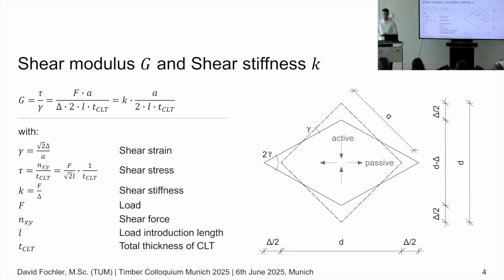And on top of that, as long as we stay with small displacements, we can calculate the resulting shear stiffness and the shear modulus using simple geometry. It's here in this equation, because the shear modulus is the shear stress divided by the shear strain. And in this process, we even can calculate the shear stiffness here. It's the force divided by the displacement, the delta. And one important thing is we have the active direction, it's the direction of the force, and the passive direction, it's perpendicular to the initial force.